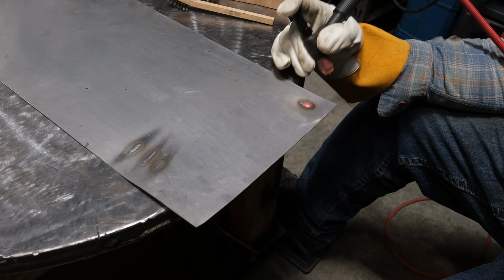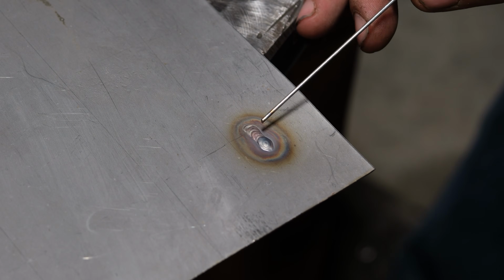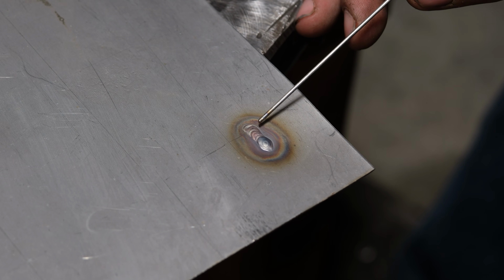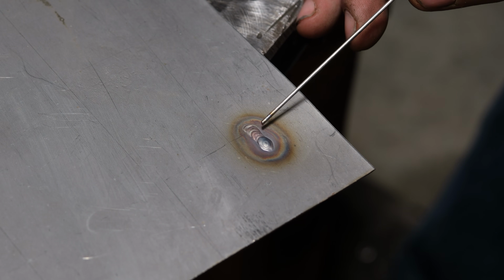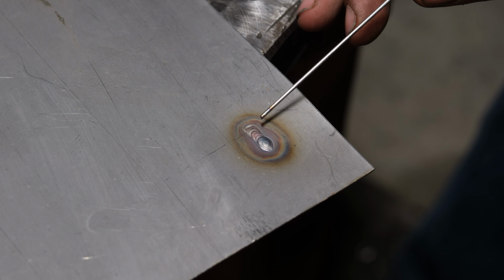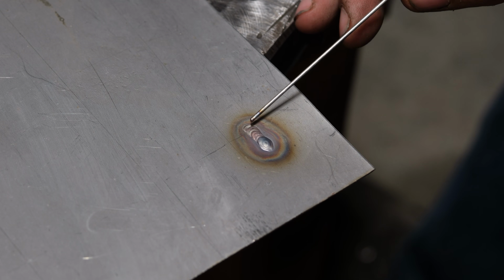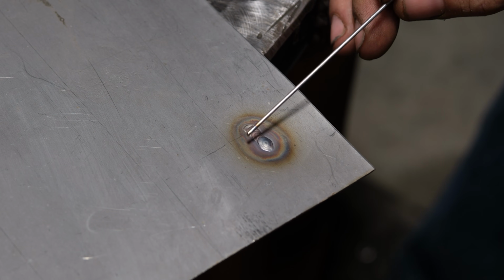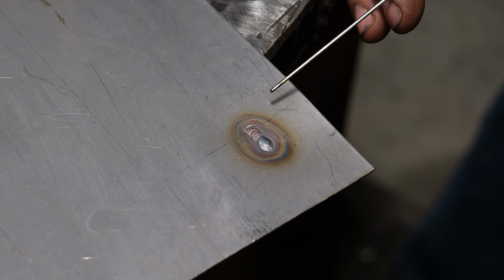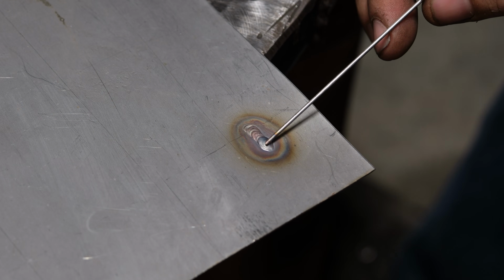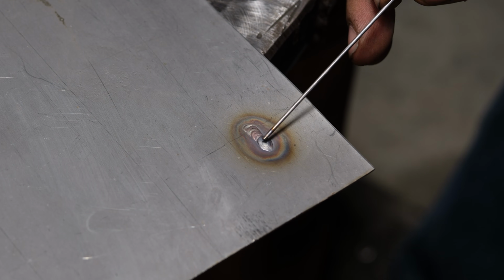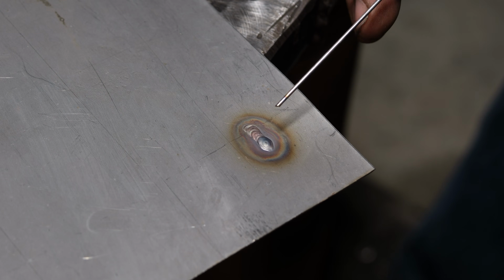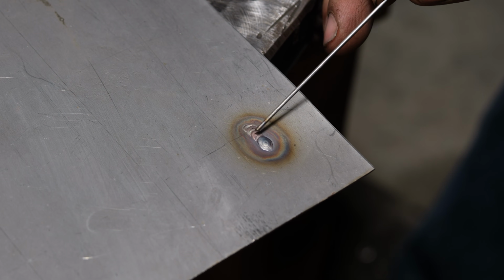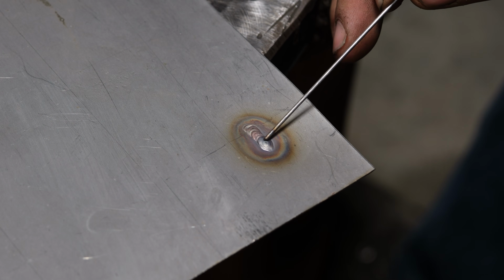So here's our little weld that looks a lot different than the previous ones. Now I did this with a number 8 cup, but yet this looks like it's kind of cooked. And no, it's not dull gray to the extent that you could definitely cook this to, but this doesn't look good. This dull red gray in the heat affected zone is a great sign that your gas coverage was poor. We have dull gray at the termination of the weld because as I was welding, I stopped and I pulled the gas coverage off while it was still hot. That's something you never want to do with stainless. At the end of a weld, make sure you keep that gas cup and the gas flowing to keep protecting that.